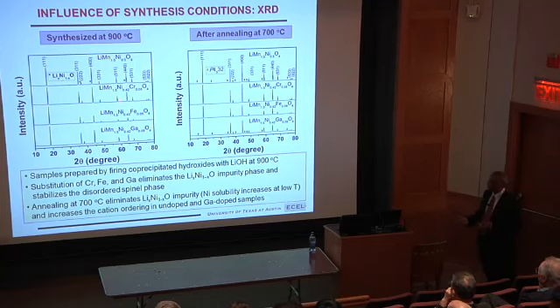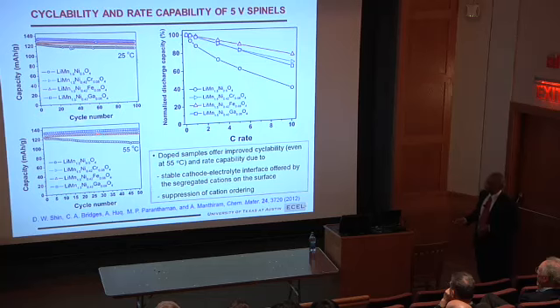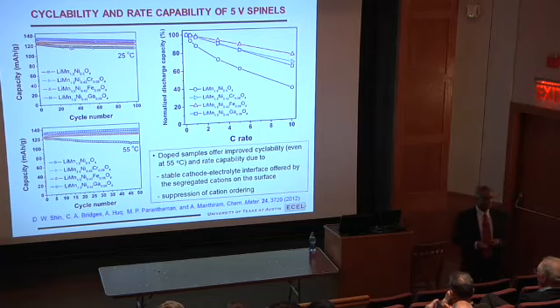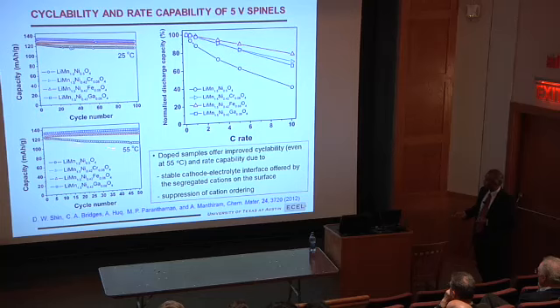Interestingly, you put a small amount of any one of these dopant ions, even at high temperature, no nickel oxide impurity and no ordering. Doping with a small amount eliminates the ordering between manganese 4+ and nickel 2+. It also eliminates the impurity. Everybody who sells the battery has to demonstrate the performance at high temperature, 55 degrees C, because I'm in Texas. I go out in the summer to my car. It's already like a furnace. So if they cannot demonstrate, they cannot sell the battery. So if you do it at room temperature, you can't find much difference. But if you do it at elevated temperature, this is the undoped. This is doped with any one of these.